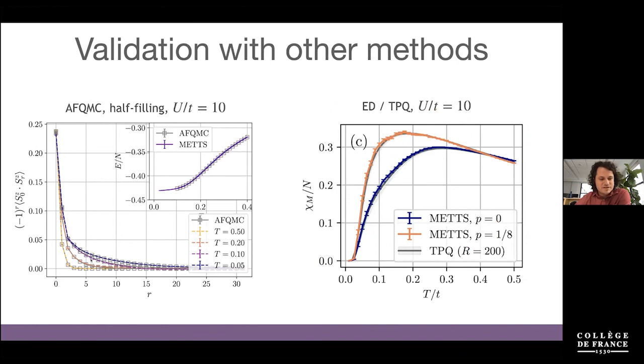We can compare the spin correlation functions shown here at different temperatures with AFQMC, which are the gray boxes, and we see perfect agreement. We can compute the energy as a function of temperature. Again, we get a very nice agreement. And a similar test, we can simulate this on smaller lattices. So we can simulate this on a 4x4 lattice using exact diagonalization.